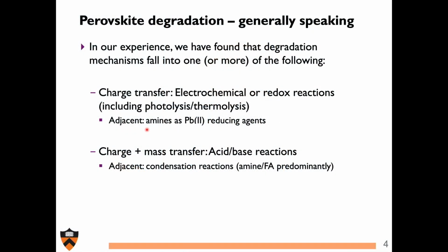And I think the primary lead reductant is an amine, which is actually the product of the other main degradation reaction, which is an acid-base reaction or something involving protons. And so you have a lot of organoammoniums in these systems. If it's deprotonated, you can make an amine. And I think that's the primary redox reagent for lead. But I'm not going to get into that today.